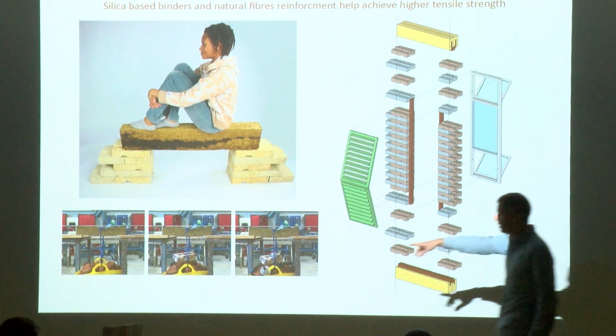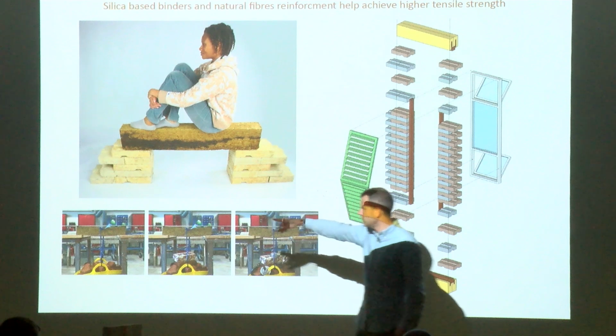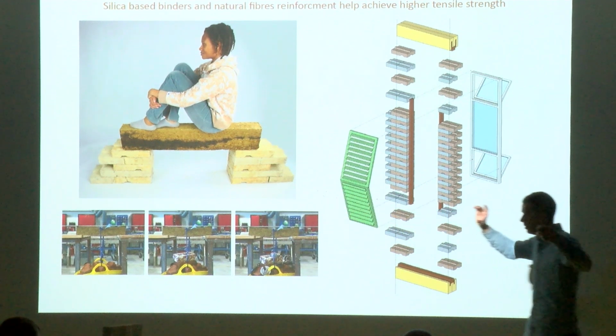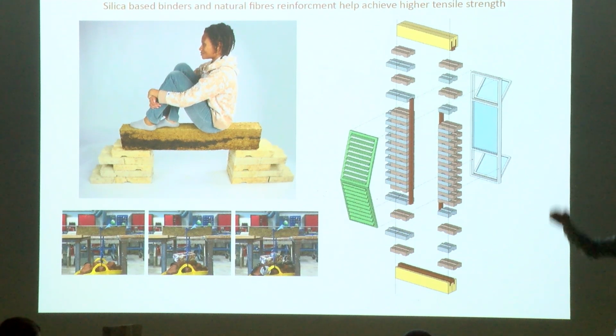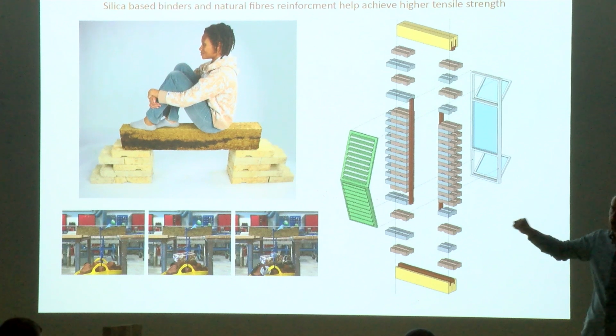So here is the testing that we did in the university. It's a 3-point load testing, so it's supported at 2 points on the sides, and then you put the load in the center, and then you add load, and you measure how much the material is deforming.